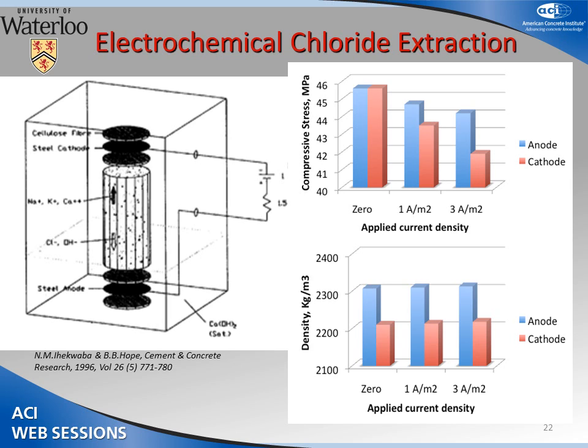But nevertheless, with the current, there was a slight increase in density for both areas, but in this case, with the compressive stress, the stress in the cathodic area decreased significantly more than the strength in the anodic area. That was just one of many of the projects that he was involved in.